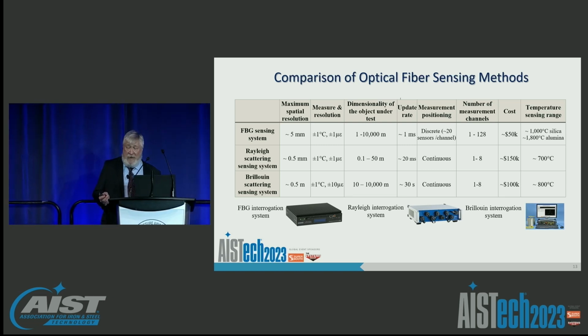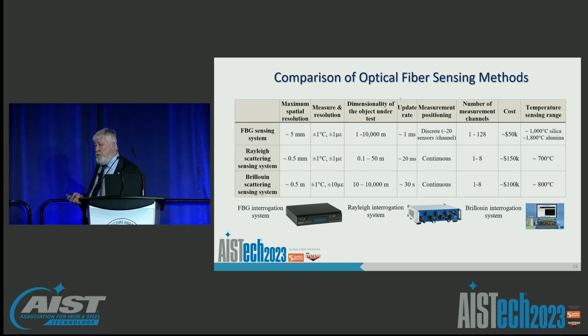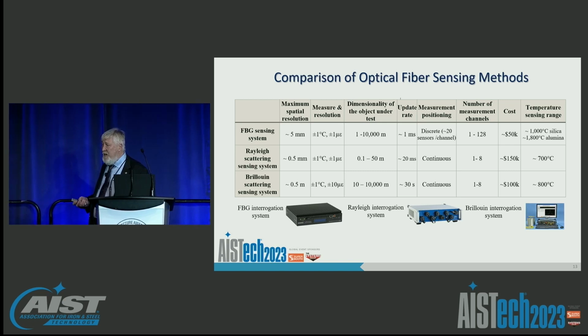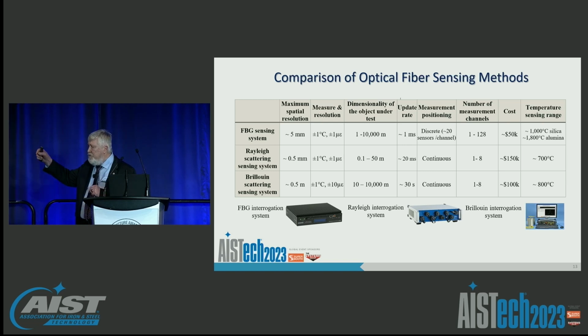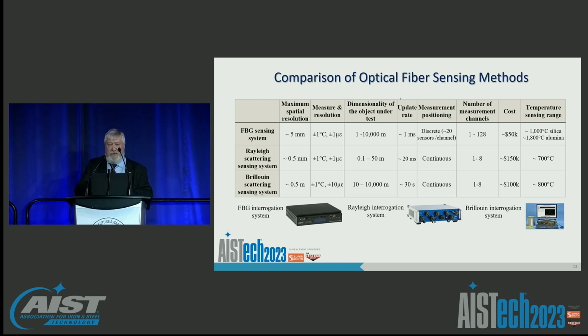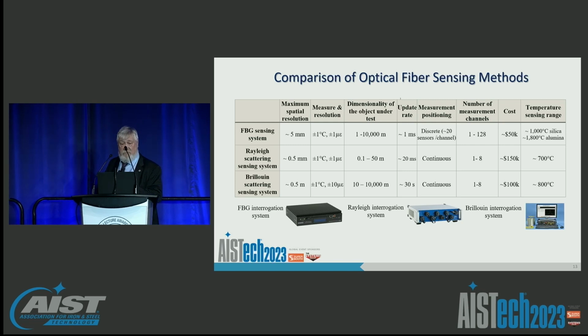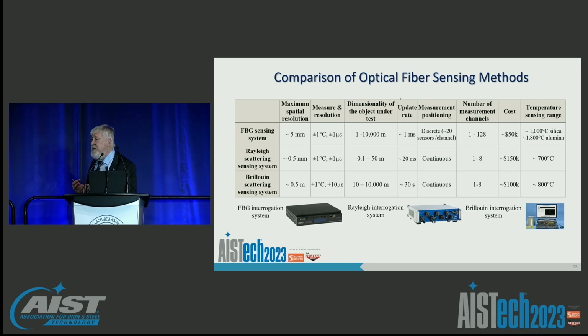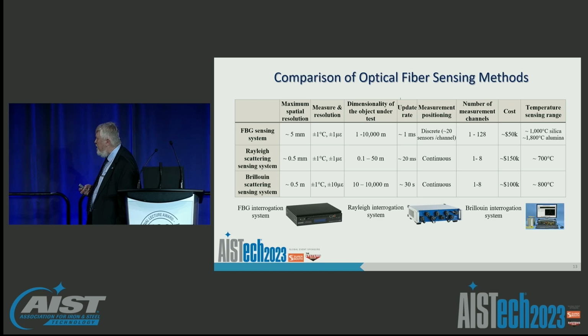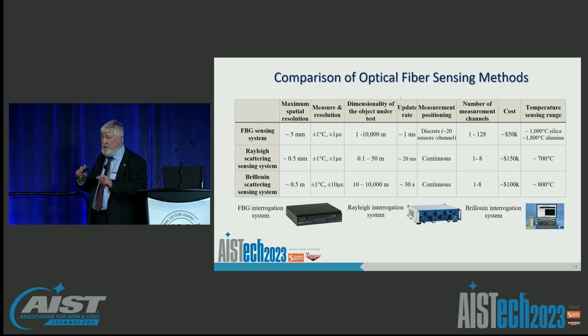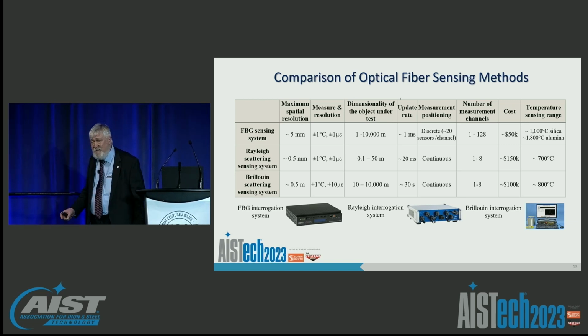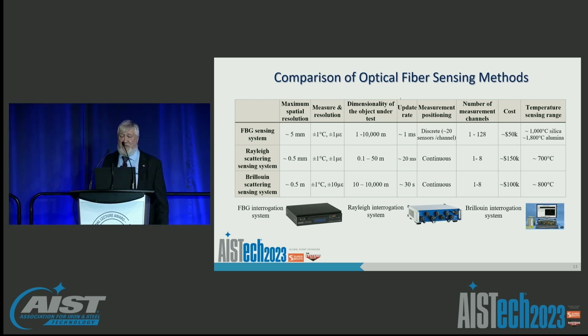The other thing about Bragg gratings is that they can be used not only in single mode, but they can also be used in multi-mode fibers, where the core is so thick that you have multiple light paths, and you can no longer use time of flight for position measurement. The frequency defines the position based on the frequency you set along the fiber. And these fibers can actually reach temperatures up to 1800 C if you use certain fiber types, like single crystal sapphire fibers, which can now be grown in up to 2-meter lengths. So I'll show you some examples of that as well.